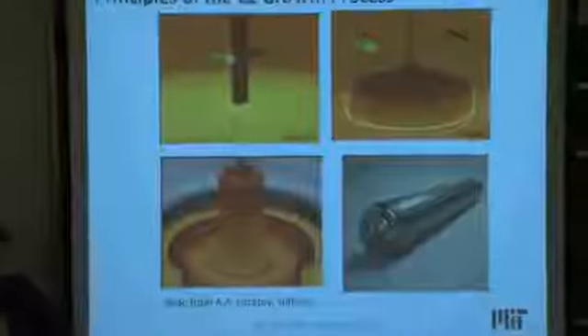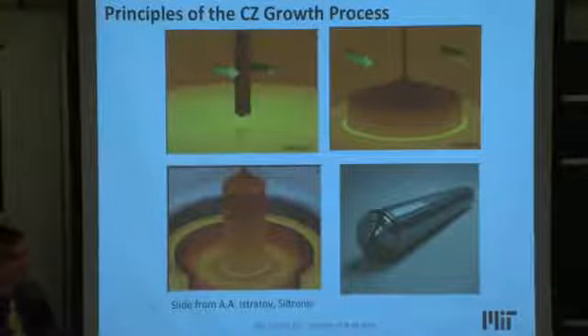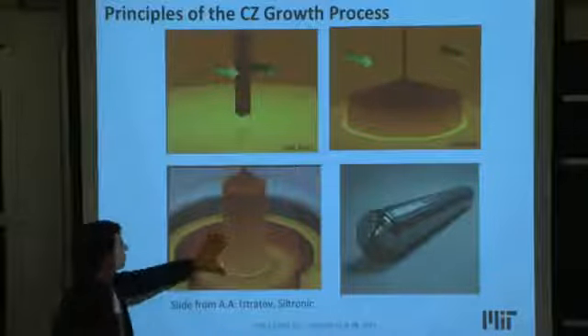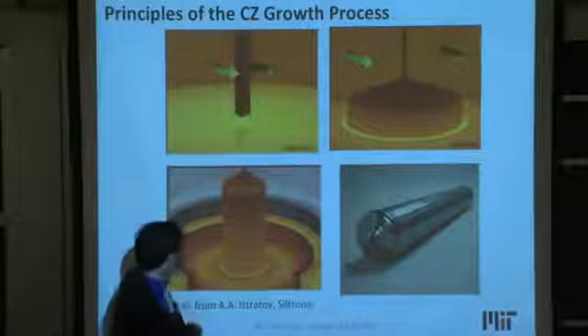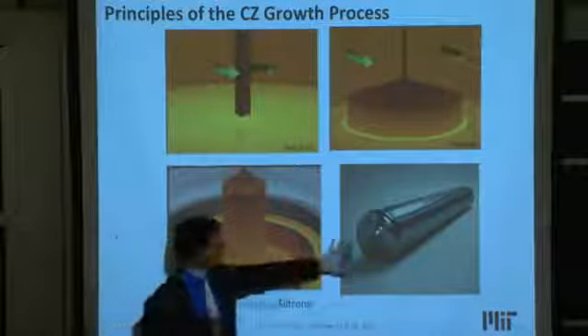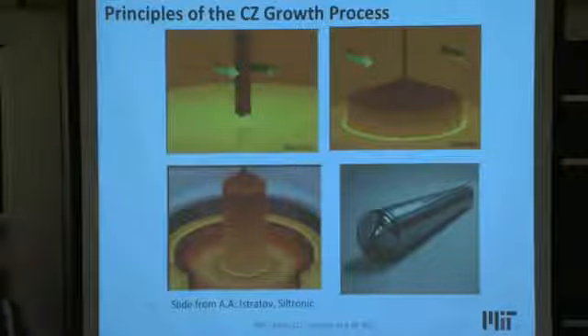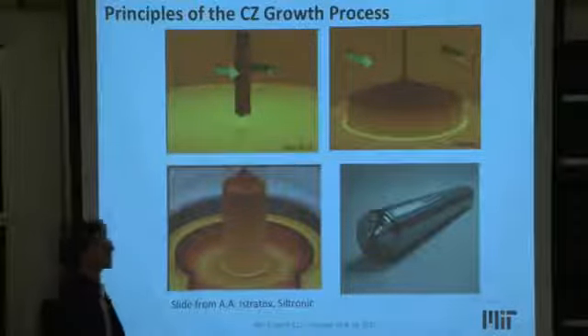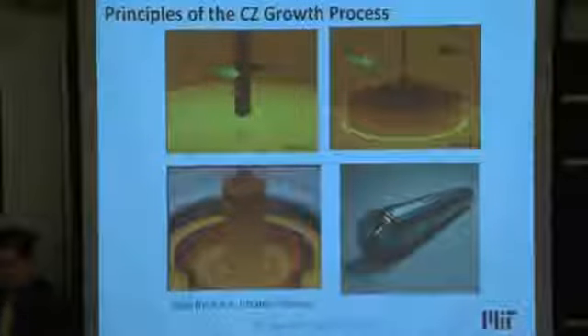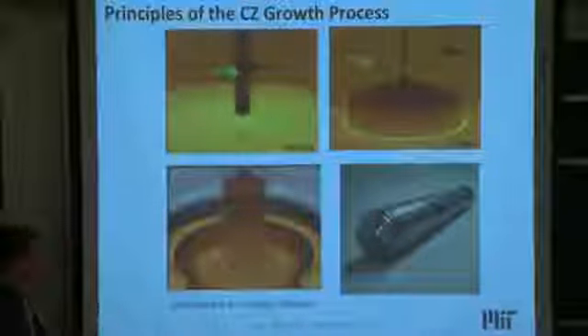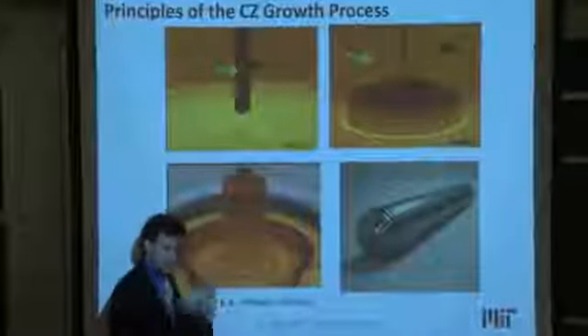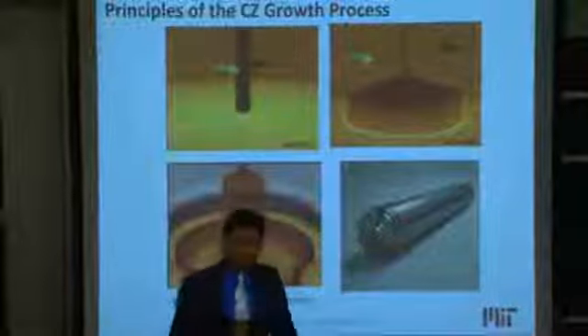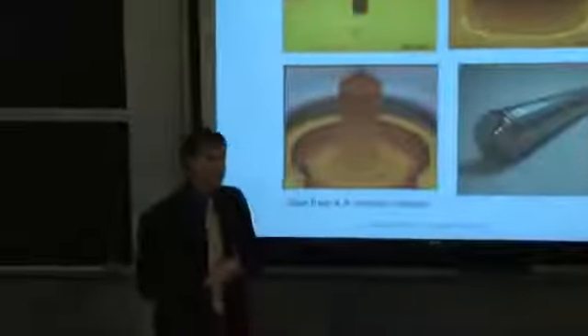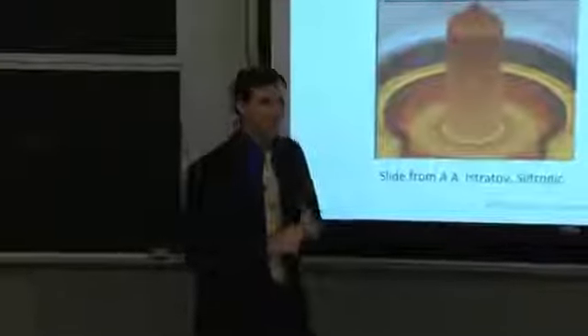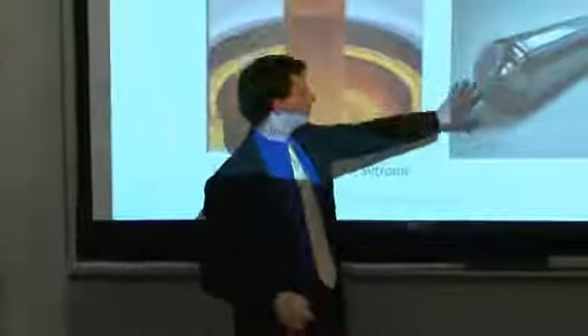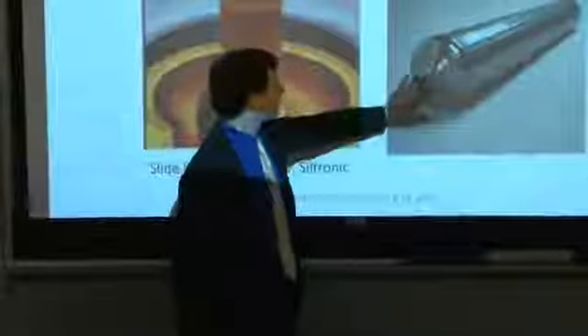Right? So if you weren't to apply, say, a shear force on your silicon, but just apply an axial load, you could support a very large weight underneath it. So the boule of silicon is grown from the bottom, and eventually you wind up with this nice ingot, as shown right there. The art that goes into growing this properly is amazing. I'll highlight it with one small example, to illustrate the bigger picture that a lot of effort goes into making these quote-unquote defect-free crystals. They're called defect-free because they contain no grain boundaries and no dislocations. They have impurities. They have intrinsic point defects, meaning vacancies or interstitial atoms, but they don't have grain boundaries or dislocations, and so they're called defect-free silicon.